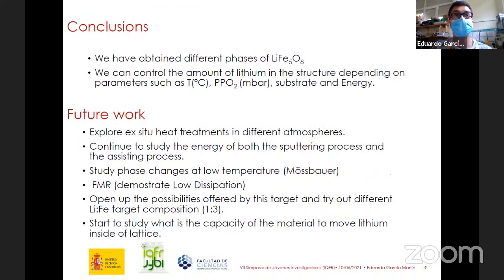In conclusion, we have obtained different phases on LFO, and we can control the amount of lithium and the structure depending on the parameters like temperature, pressure, oxygen, substrate, and energy.